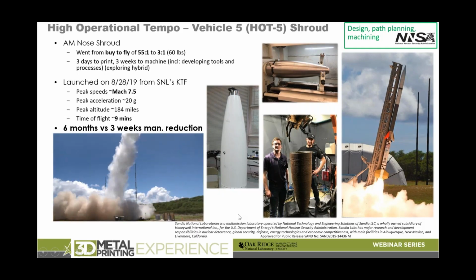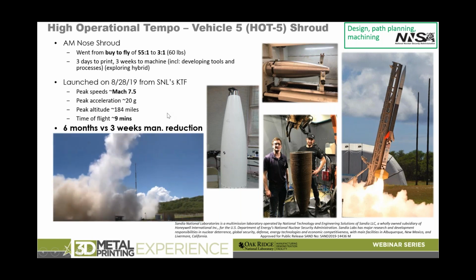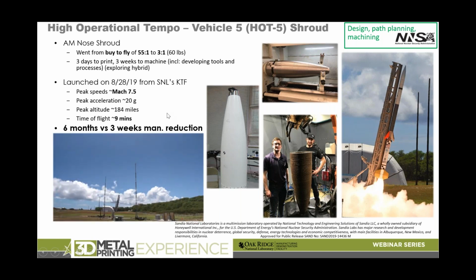This is one of my favorite demonstrations. There was a rocket that needed to be launched, but they did not have a nose cone, and they were quoted a 6-month lead time to get a nose cone for the rocket. These are supply chain issues that have been happening in recent years. So what we were able to do is actually print this nose cone in 3 days. And then it took 3 weeks to machine, and that's only because it was a custom setup.